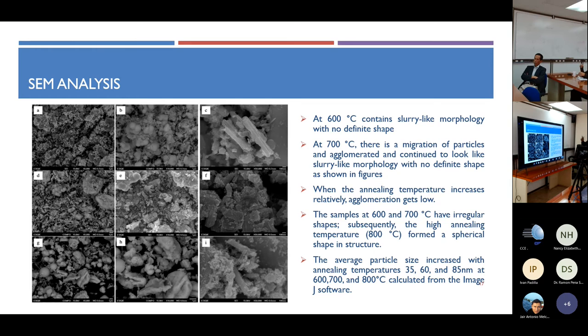The same analysis, for 600, 700, and 800 degrees Celsius, with different magnifications: 2000, 5000, and 50,000 magnification. You can see that at 600 degrees Celsius, it's a slurry-like structure and agglomerated.